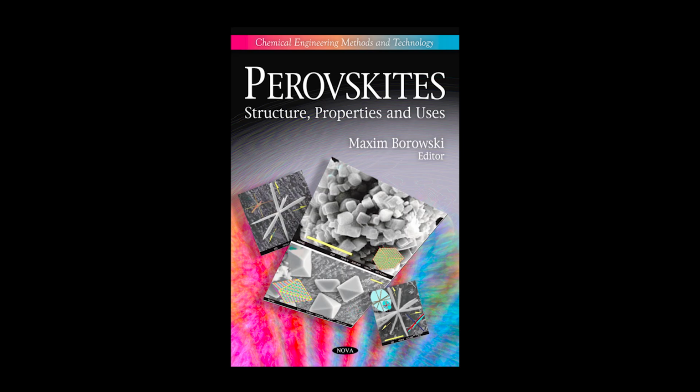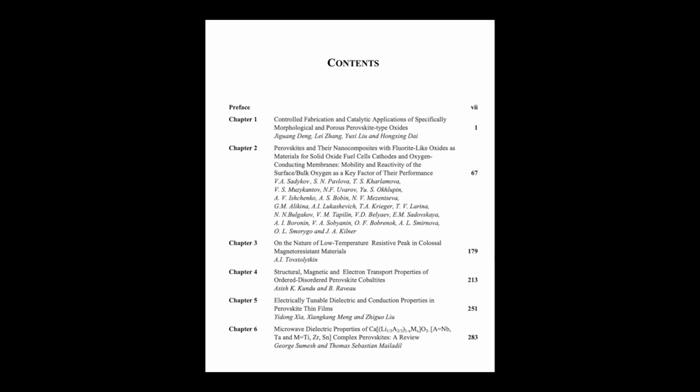This is likely due to a combination of factors. The inherent stability of the Co-O bond might be higher, and cobaltites naturally tend to have more abundant native anion vacancies, which might be less susceptible to forming strongly bound detrimental surface hydroxides that block active sites. Furthermore, researchers found that adding a small amount of copper, Cu, as a dopant into the LaCoO3 lattice could further improve its resistance to water vapor.